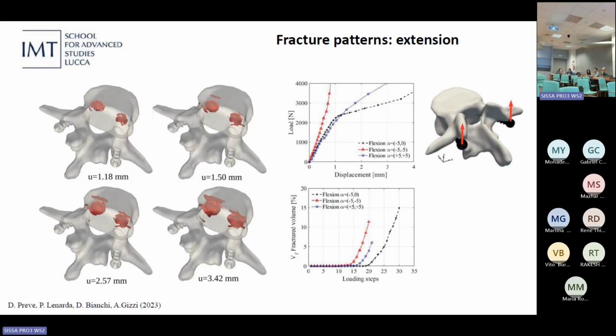This is the analysis for the other loading conditions. So we had the case of extension, where the load was applied to the head of the screws in the upper direction, and we can see a similar evolution of the damage inside the cortical part of the bone, in particular those semi-spherical regions which are increasing inside. And we can also vary the angles of those screw implants, and measure the load displacement curves for different angle orientations, and also the evolution of the fracture volume inside the bone.